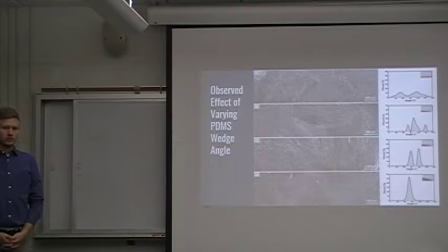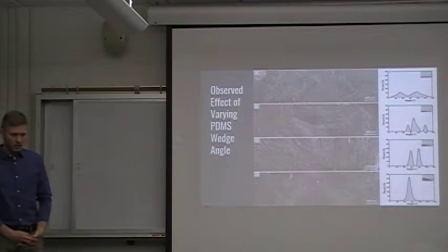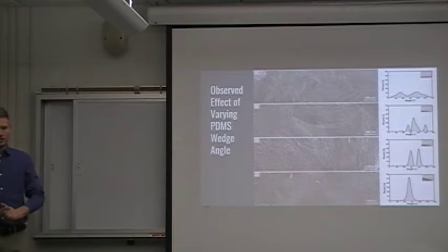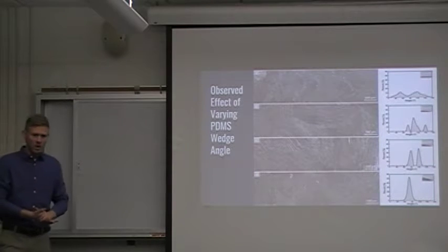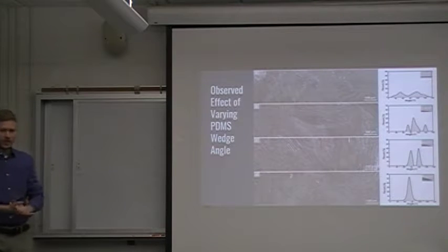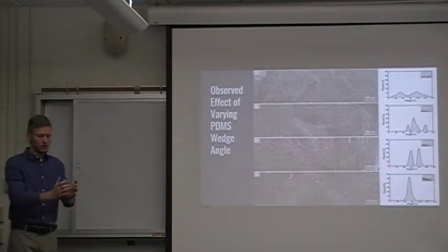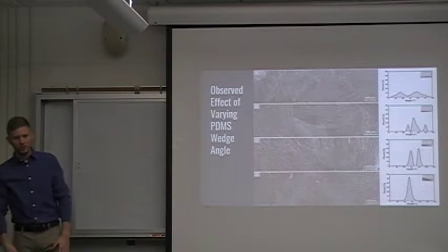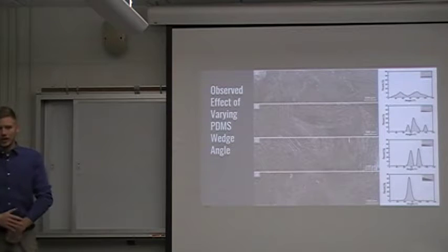Now, these wedges, how do they make the wedges? It is a polydimethylsiloxane, and it is a mixture, and it is poured into a mold, and it is then solidified. Okay, so the mold basically determines the angle. The mold gives it the angle, they pop it out, and then they put it into a container or a reservoir, and then they pour the suspension, the polyvinyl alcohol, graphene oxide on top of it, and they cool it cryogenically with ethanol.